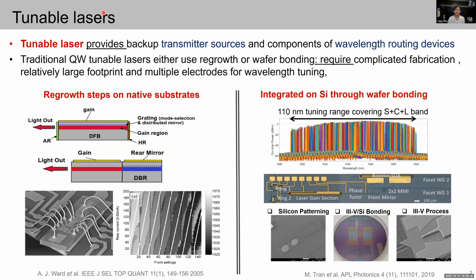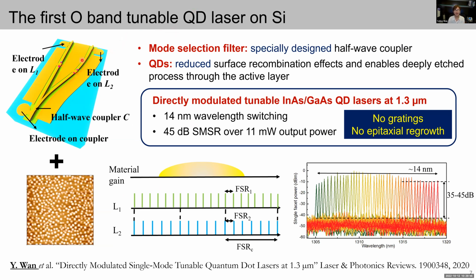In addition to microring lasers, widely tunable lasers are also an important branch of lasers that can provide backup transmitter source and components of wavelength routing devices. Traditional tunable lasers use quantum wells as the active region and are typically fabricated through regrowth steps on native substrate or integrated on silicon through wafer bonding. These structures both require complicated fabrication, have relatively large footprint, and also have multiple electrodes for wavelength tuning. But here we use a specially designed half-wave coupler as a mode selection filter, and we leverage quantum dots' reduced surface recombination effects to enable a deeply etched process through the active region.